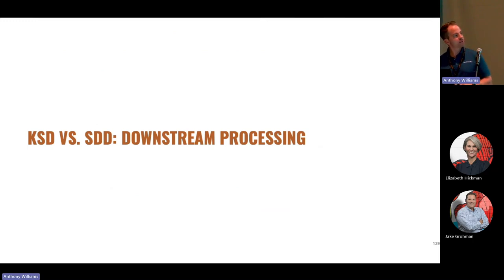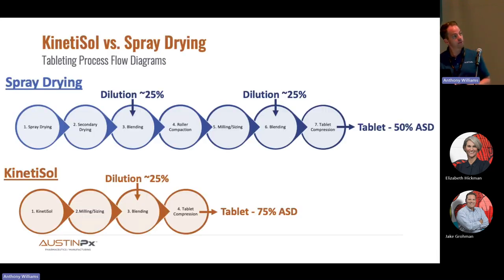My final segment in why KinetiSol is the greatest thing since sliced bread is to compare KinetiSol to spray drying in terms of downstream processing, specifically tablet formation, because I don't think it's trivial that KinetiSol dramatically reduces the process flow in going from amorphous dispersion to final tablet. So spray drying is a series of typically 7 steps, starting with spray drying, secondary drying, addition of external excipients, which is a dilution step that I just sort of picked a midpoint. I think 25% external excipients at the roller compaction phase might be a nice midpoint. Could be less, could be more.